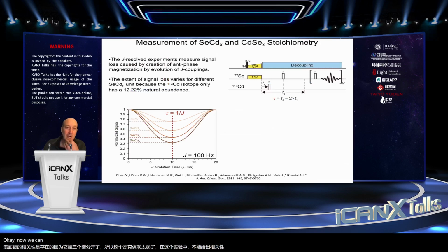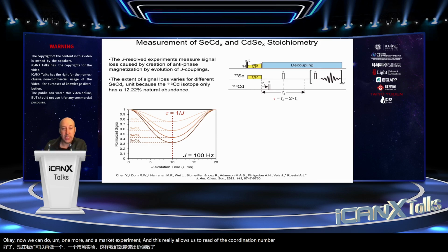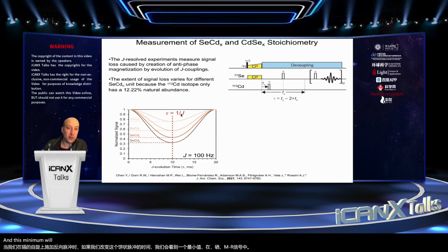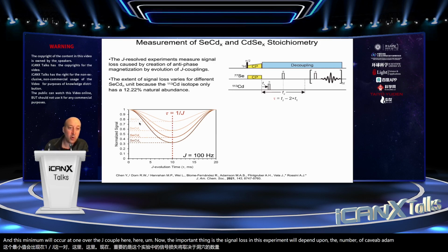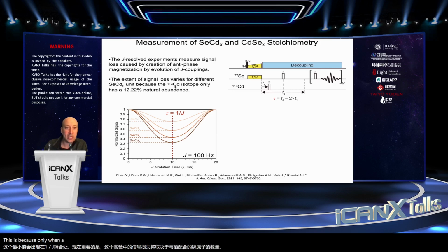Okay, now we can do one more NMR experiment, and this really allows us to read out the coordination number and determine what's bonded to the cadmium and selenium atoms. This is known as a heteronuclear spin echo or a J-resolved experiment. What we're going to do is observe selenium while we apply an inversion pulse on the cadmium spins. If we vary the timing of this pi pulse, we'll see a minimum in the selenium NMR signal, and this minimum will occur at 1 over the J coupling. The important thing is the signal loss in this experiment will depend upon the number of cadmium atoms that are coordinated to selenium. This is because only when a selenium has a cadmium-113 attached to it will we see this reduction in NMR signal.